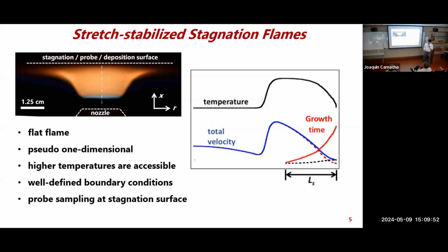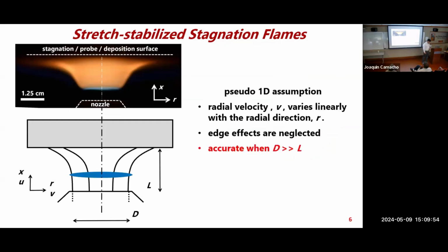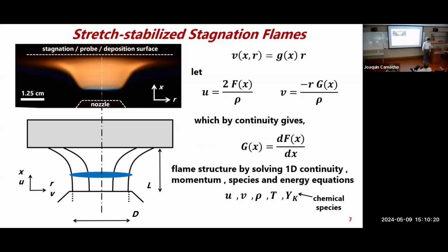As a matter of fact, the formulation that Professor Williams and Seshadri have been working on for a long time is using this counterflow type flow field and using an assumption. Actually, von Karman was credited with first introducing a similarity solution where you can reduce this axisymmetric 2D flow field into one dimension effectively. By making some assumptions of having a nice wide aspect ratio, you can combine the radial velocity with the axial velocity if you assume this linear function here in R.